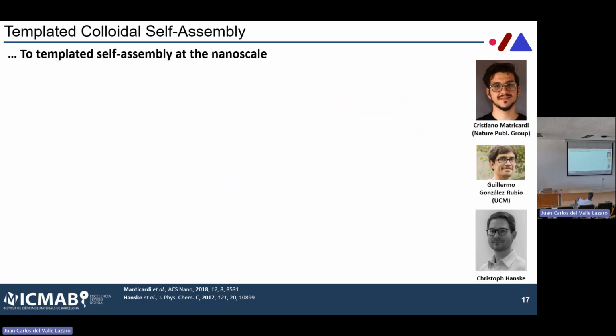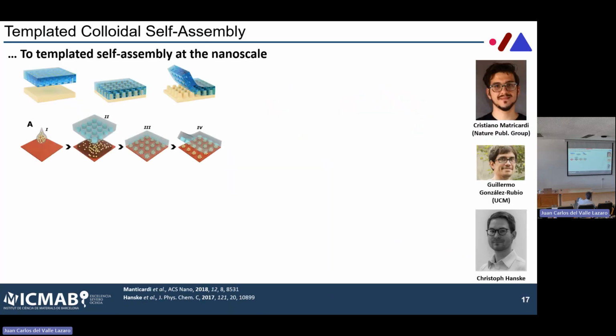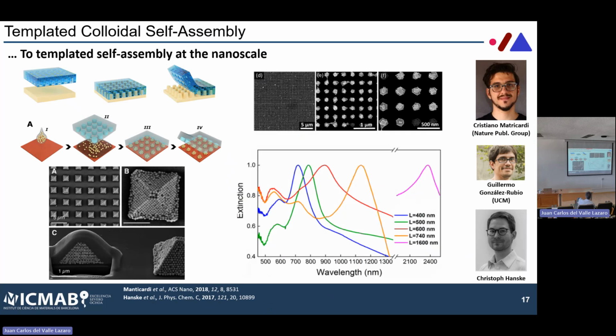And then, more recently, this has moved to the nanoscale. So now we can create these types of structures where you start to have nano architectures that enter the nanoscale, and so we start to see a complex response. So here, as you can see, by changing the distance between these arrays, we can move these lattice plasmons in different ways. Again, these are not very exciting because these are still broad. Okay, we always want something sharp.